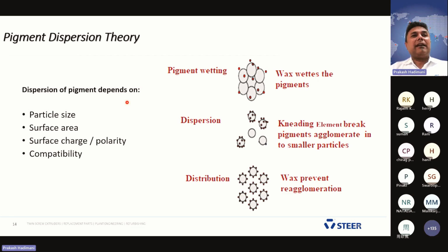In the dry pigments, again, how can we wet each pigment? Each pigment has to be wetted thoroughly so that the dry pigment can be mixed in the polymer. How to wet the pigments? The pigment dispersion depends on your particle size, whether a coarse size or a small fine size, and the surface area, which is very, very important. And surface charges, again the polarity on the surface, and the compatibility of the pigments with the polymer. It has to be compatible. If you're using non-polar polymers, again you need to find out the compatibility to bind together.